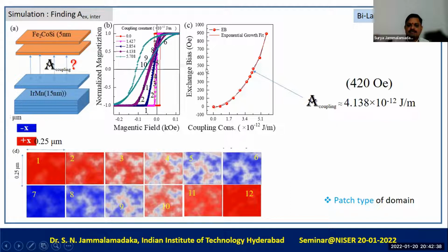This 420 Oersted value exactly matches with the coupling constant of 4.138 into 10 power minus 12 joule per meter. Okay. So this is the amount of coupling strength that exists between our ferromagnetic and antiferromagnetic layer to obtain an exchange bias value of 420 Oersteds.